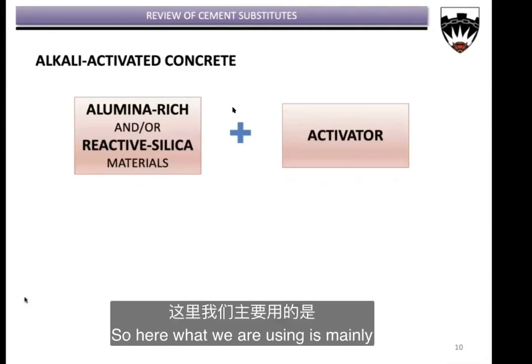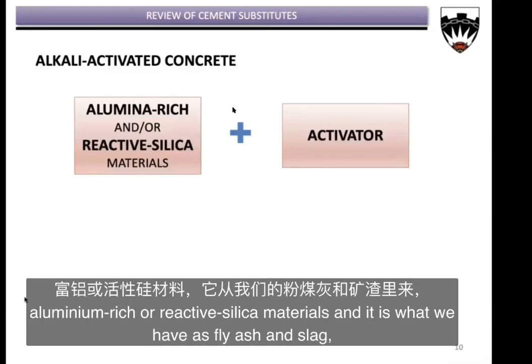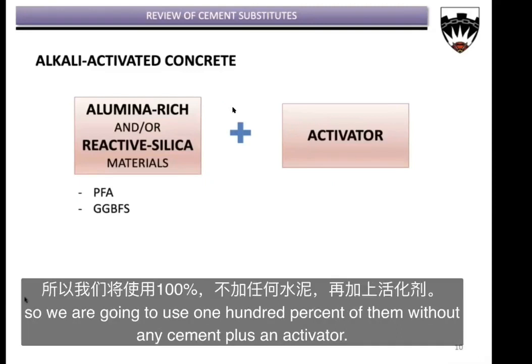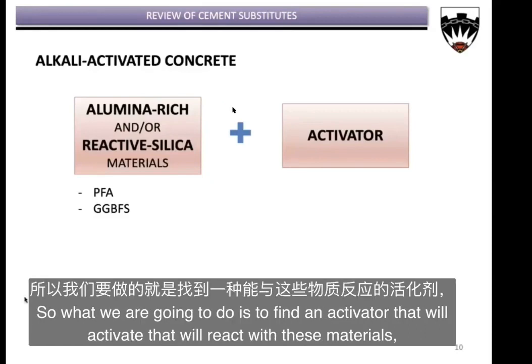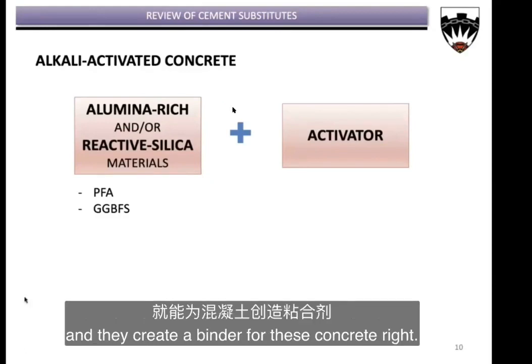So here what we are using is mainly alumina-rich or reactive silica materials, right? And it is what we have as fly ash and slag, right? So we are going to use 100% of them without any cement, plus an activator. So what we are going to do is to find an activator that will react with these materials, and they create a binder for this concrete, right?